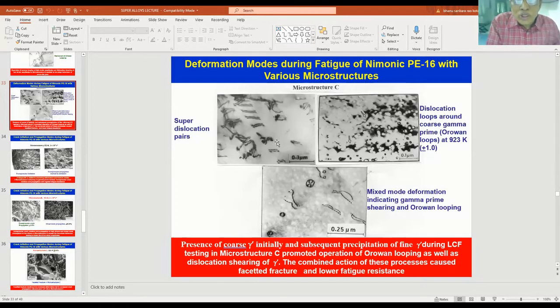When during service, if some gamma prime is getting precipitated, they will be very fine, and that will be cut by the dislocations passing through planar slip bands. You can see dislocation pairs there. This is the indication of gamma prime getting cut, because the precipitates are very fine. You cannot see the fine precipitates.